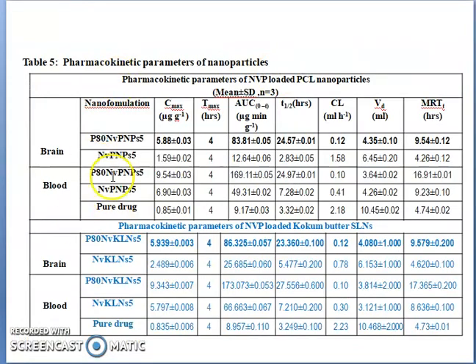Next, the pharmacokinetic parameters. We have seen the Tmax, the maximum, at 4 hours. In all the cases at 4 hours, maximum concentration of the drug was observed in the brain as well as in blood. The Cmax was 5.88 in brain for polymeric coated nanoparticle and 5.939 for coated lipid nanoparticle. Maximum drug was obtained in comparison to the uncoated and pure drug. So we can say the Cmax was obtained at Tmax.